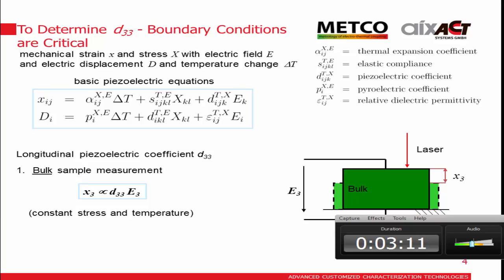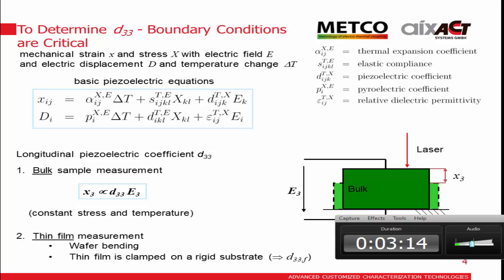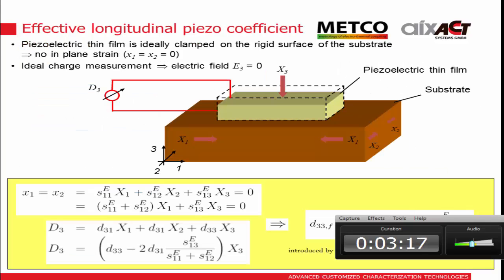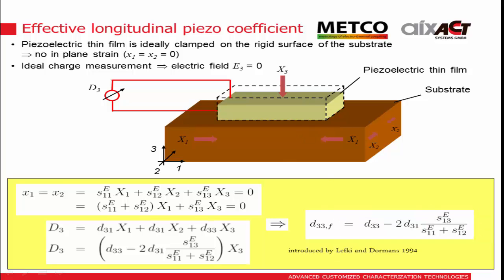If we go over to thin films, we have additional issues. The difference here is that we have a substrate on which the piezoelectric material is put. The substrate will clamp our piezoelectric material, giving us a different coefficient because it blocks the lateral motion. So the effective D33, or effective strain, that we measure on the film is reduced by this clamping. We receive an effective coefficient which is reduced by the D31 and the compliance of the film.